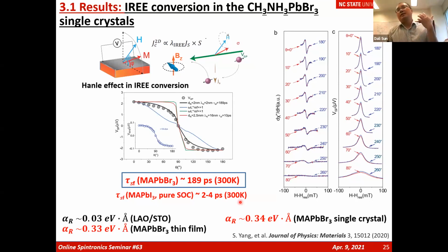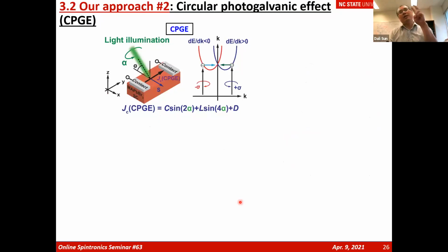But spin-to-charge conversion is still harder to use to determine the Rashba effect, because it's an indirect conversion that happens later in the Rashba state. It's not related directly to the band structure. So that's why we're using our second approach, the circular photogalvanic effect. This effect is really connected with optical transition due to different helicity of the light illumination. This method has been traditionally applied to investigate 2D electron gases and topological insulators.